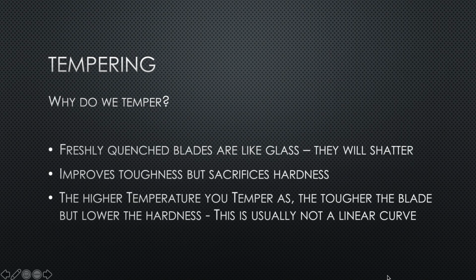So next is the temper. So why do we temper? Basically a quenched blade is going to be like glass. You drop it on the floor, it's going to shatter. We need to improve the toughness of that blade so it's not quite as brittle. But we still want to retain the edge, and we still want it to be hard. So it's kind of a fine balance. The higher the temperature you use in the temper, the tougher your blade, but also you're going to lose more hardness. And these are usually not a linear curve. Each of the steels typically will have a curve that shows you the different temperatures and the hardness you can expect.